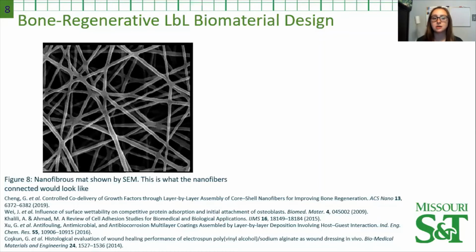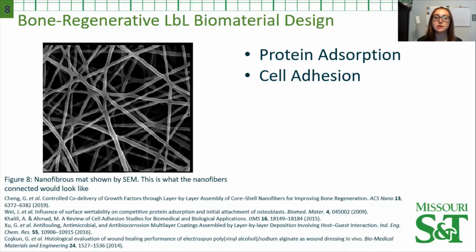In bone tissue engineering, some protein adhesion is desired for cell proliferation. It is believed that the balance between proteins adsorbed to the surface and cell adhesion correlate. There are both adhesion-promoting proteins like fibronectin and adhesion-inhibiting proteins like albumin, so it's desired for adhesion-promoting proteins like fibronectin to adsorb at a higher concentration. Then, cell adhesion is tested to see how well cells will adhere and grow on the surface. Also, cell studies determine the biocompatibility of a material by seeing how many cells are alive or dead.